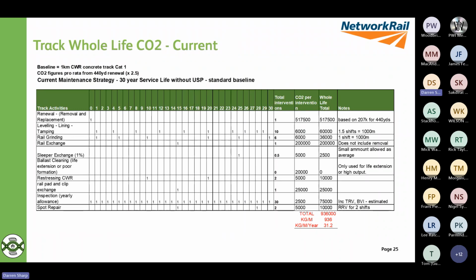So along the top, we've got 30 years. We've got the cycle rates in as we go down each one of those activities. So we have one renewal, then there's tamping, grinding, and so on, rail exchange. So we can then create a CO2 figure for that. We can look at the total CO2 figure, and we can also calculate a whole life total there. So in terms of kilograms per metre per year, we've got 31.2 there. So that's our baseline rate.